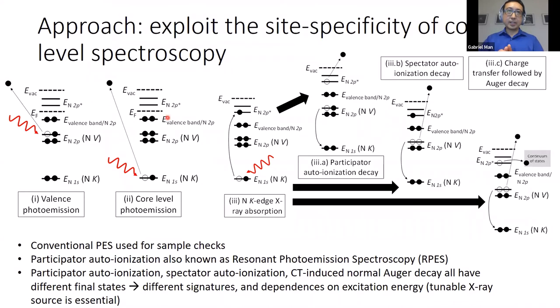So in this work, I've now exploited the site specificity of core level spectroscopy. This schematic shows all of the spectroscopies used in this work. Conventional photoelectron spectroscopy, shown here as valence photoemission or core level photoemission, is really used to ensure that the sample that we're measuring is really what it's supposed to be, because this class of material is so sensitive to beams.